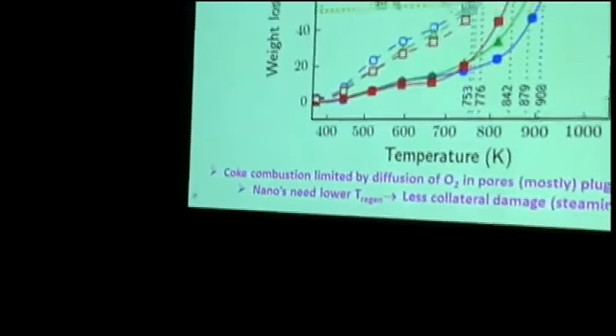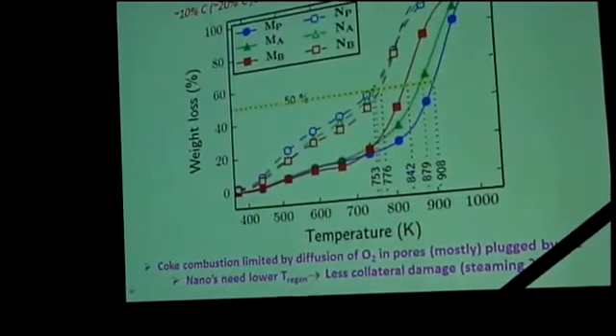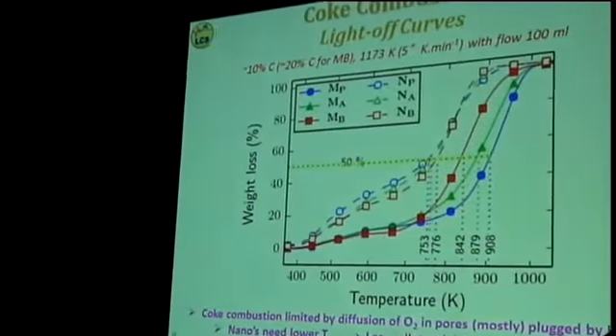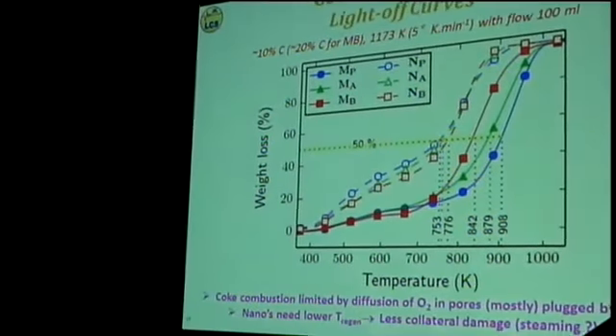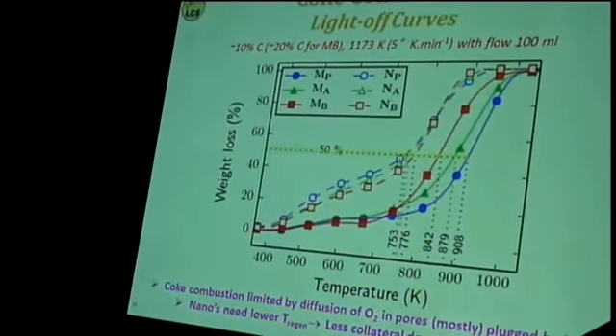Of course, the obvious explanation is that the coke combustion is limited by diffusion of oxygen into the pores, and we have seen that for some of the zeolites the pores are totally blocked, so it's a much more difficult process. With the nano-sized zeolites, if you want to remove, let's say, 80% of the coke, you have to go to a much lower temperature, and so the potential for collateral damage, such as steaming during the decoking, is much less with these materials.